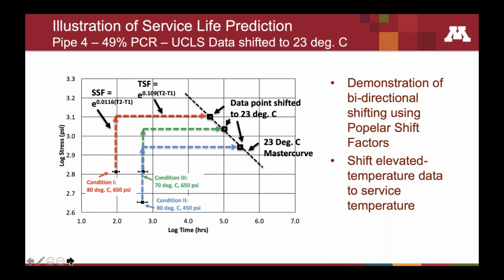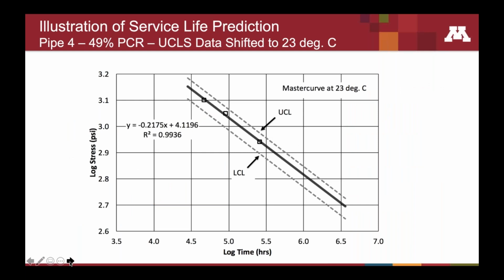And this would be the prediction of how long this pipe or this material will last as a function of stress on the y-axis and time at 23 degrees C. If you wanted a different temperature, again, this curve would be shifted out to the right for lower temperatures, to the left for higher temperatures. We then established upper and lower confidence limits on that curve based on the scatter in the data.